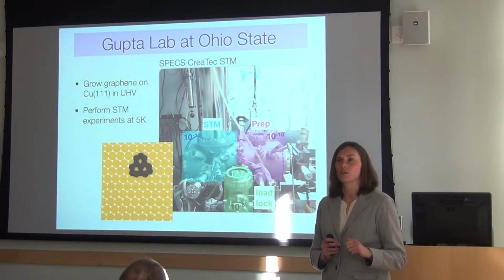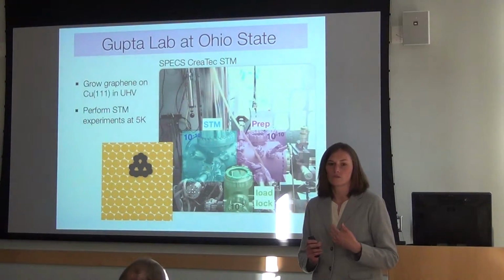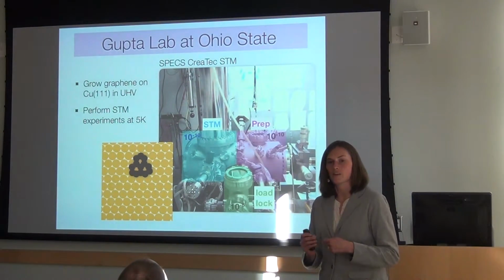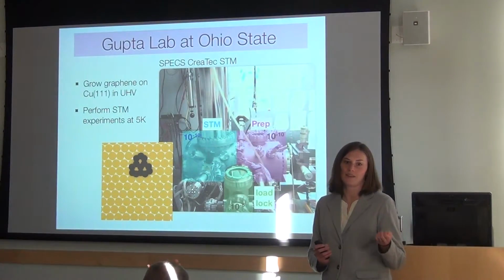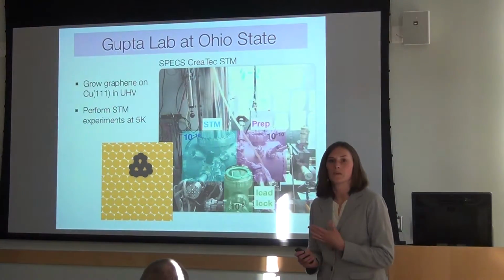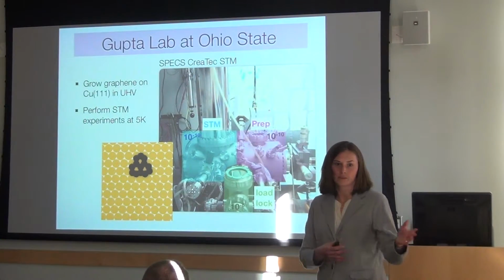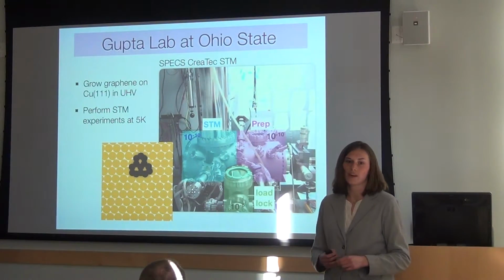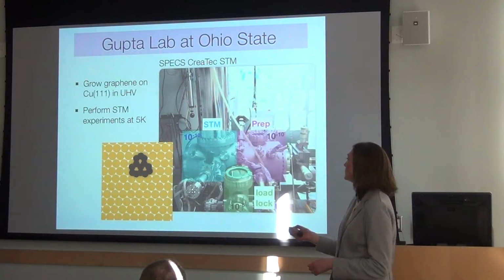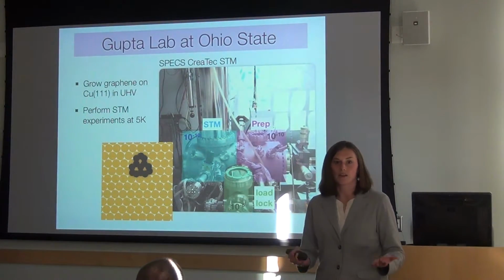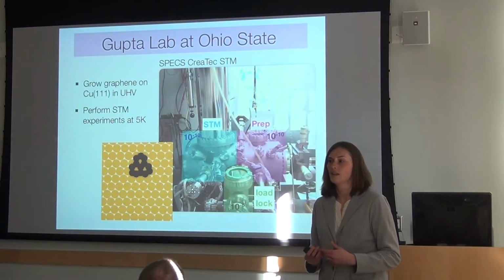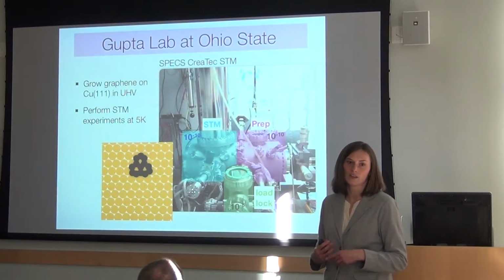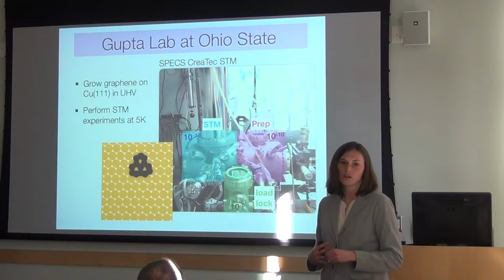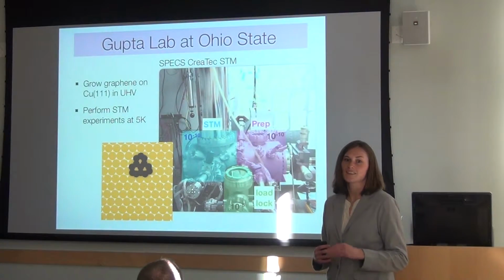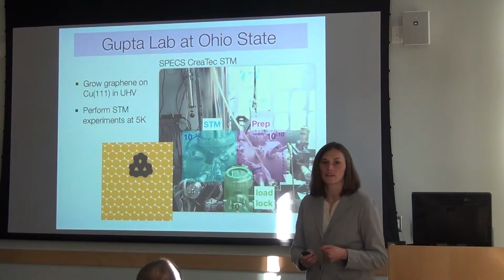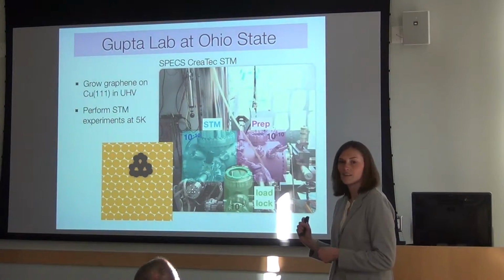And that's just a random process. So you can figure out how many atoms are going to hit your sample in the time that you have to transfer it into the chamber. So even in ultra-high vacuum, and also since we're doing this growth at 10 to the minus 5 ethylene pressure, we can get ethylene molecules to stick on it and make it gunky. So yeah, it's clean, but even still, it's not perfectly clean. We'll see. Other questions?